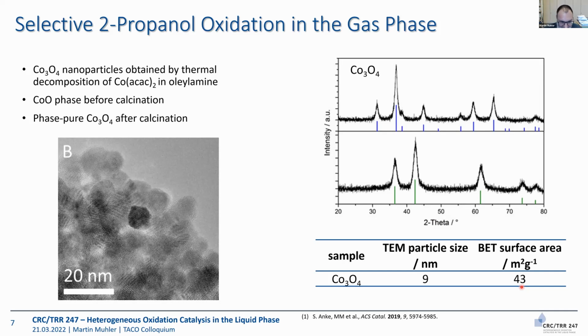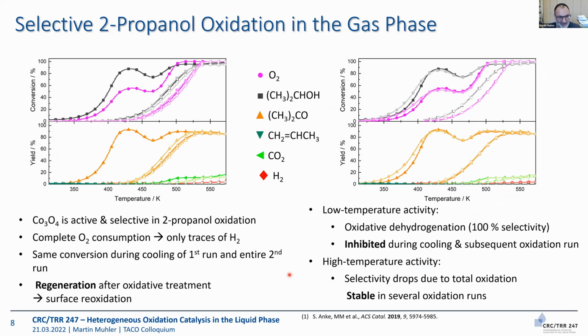In industry, you would never use such a fine powder as catalyst that only works in small reactors. In industry, you would have to use pellets, but that is then a different story because then you have to enter mass transport limitations. In our case, it's kind of a perfect catalyst for a small reactor, low pressure drop. It's a non-porous catalyst, that I should say as well. It's just exposed outer surfaces of spherical nanoparticles.